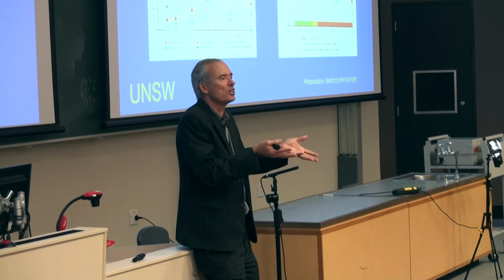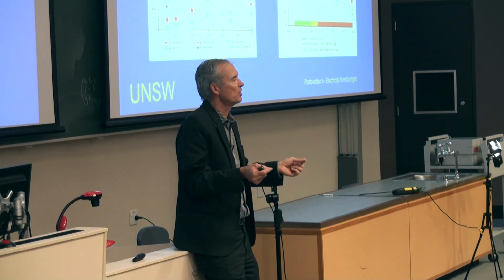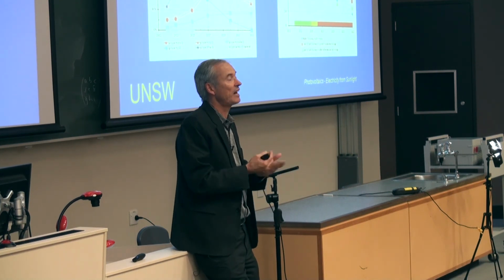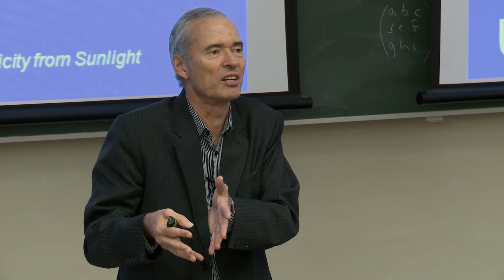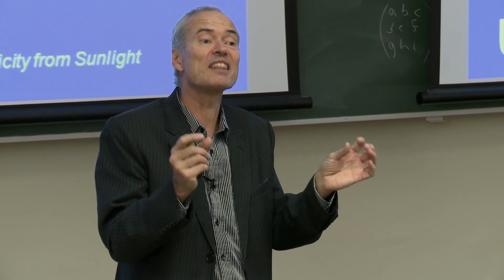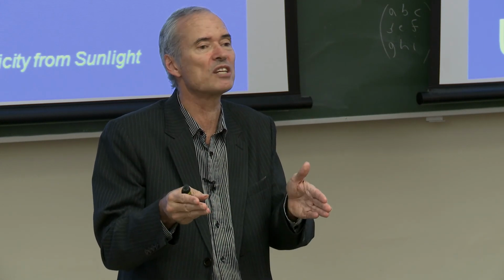Now what that means, I'm not going to go into a lot of detail, but as the silicon is growing, these impurities segregate out. They don't get incorporated into the solidifying silicon. So they stay in the molten region, but where you've got grain boundaries, you lose that ability to segregate. You segregate in the crystallizing regions. In the region behind it, it's a bit like an amorphous region. You lose the ability to segregate, so you get this collection of the impurities at the grain boundaries. So when you move to high performance multi, you're actually making grains, if anything, a little bit smaller than conventional multi, but you have to solve that problem of segregation of impurities to the grain boundaries.